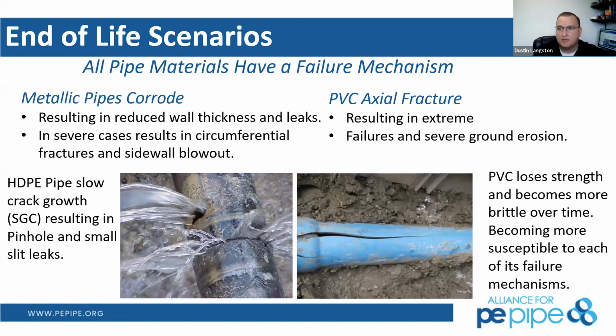And so where this is going to become very dangerous in the future is in all these pipe systems that are PVC, we don't have the typical failure that we're all used to. If we have a corroded or a circular fracture or a corroded ductile iron, we dig down, we put on a band clamp, and we're back up and running. And it's a good Band-Aid for quite a while. Or maybe you're replacing a small spool piece with 2 band clamps or a mechanical joint of some kind. We understand this, we know this. It's rather inexpensive to fix pipe doing this.